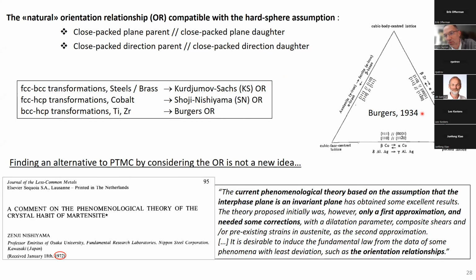It was already known by Burgers in 1934. It is represented here in this triangle, okay? Between, for example, FCC and BCC phases, we have a Kurdyumov-Sachs orientation that respects these conditions here. Between FCC and HCP, for example, in the transformation in cobalt, we have a Shoji-Nishiyama orientation relationship that respects this condition too. And in titanium, between BCC and HCP transformation, we have the Burgers orientation relationship that also corresponds to what is written here.